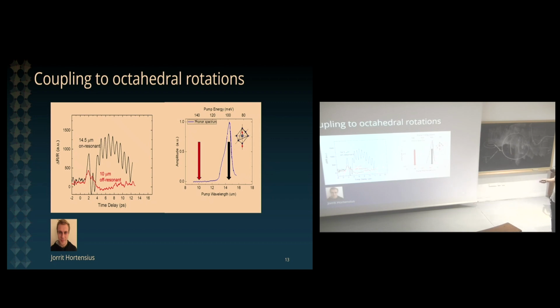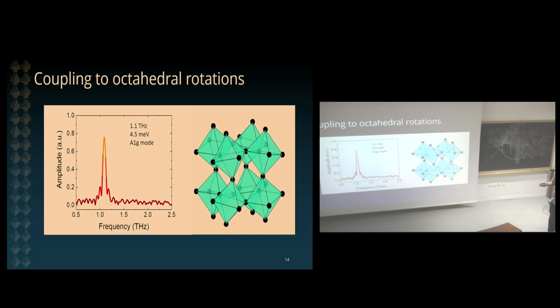However, if he chooses to tune the laser light in resonance with this particular mode, occurring at close to 15 microns, so this is an aluminium oxygen stretching mode, so the aluminium is moving inside the oxygen cage, as illustrated here, then what you already see is this very large amplitude coherent excitation. So he's exciting the lattice with a 20 terahertz pulse, and he's observing coherent dynamics occurring at 1.1 terahertz. Okay, strongly nonlinear coupling between phonon modes.